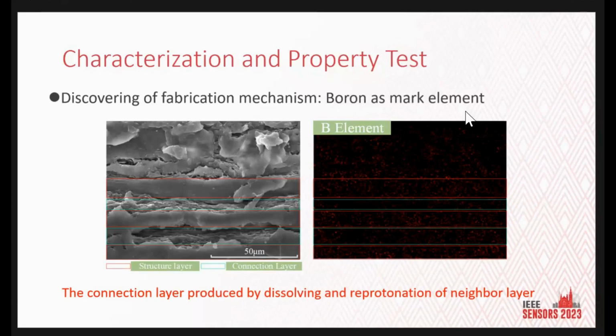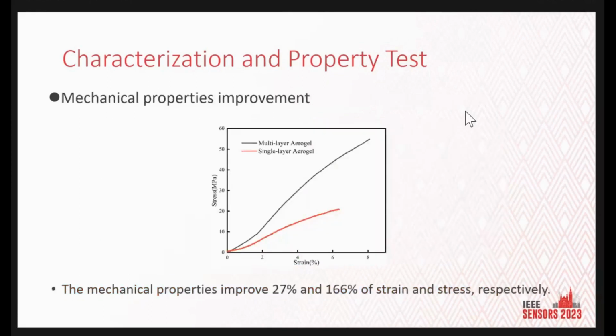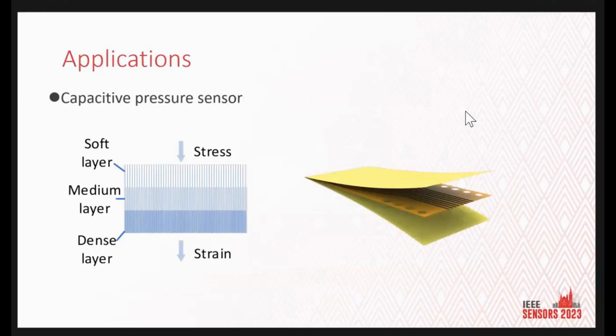But we can find that in the green box there is still the appearance of the boron element. The proper explanation is that the dispersion dissolves part of the neighbor layer, and they reprotonate again in the water to form a connection layer to connect each structural layer. And we carried out mechanical tests. The multi-layer aerogel shows a huge mechanical property improvement, and the strain and stress improved 27% and 166% respectively. Let's talk about the potential application of our techniques.